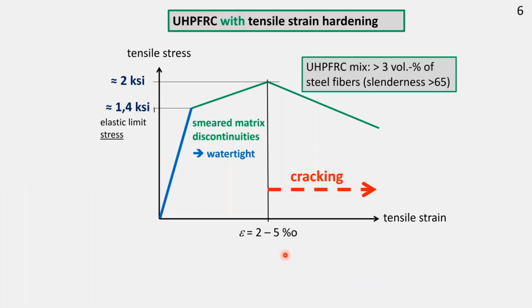Now, let me make a remark regarding the fiber content about UHPFRC with tensile strain hardening behavior. As I said, we have a relatively high fiber content in order to have this tensile strain hardening behavior. And the reason is actually serviceability. UHPFRC is in particular interesting in the serviceability domain. And in the serviceability domain, we do not have strains significantly larger than 1 per mil. So this means for deformation up to about 1 per mil of strain, we should have a material that is crack-free. In the hardening domain, the material has what I call smeared matrix discontinuities.